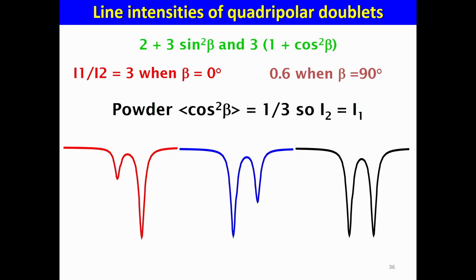The first one, when you have to consider the orientation of the electric field gradient with respect to the main direction of the gamma beam. So you will get either such a situation or such a situation, which can be rather extreme. But usually you are working with powders. So only to repeat, what is a powder? It's a random distribution of small objects, microcrystallites or nanocrystallites.